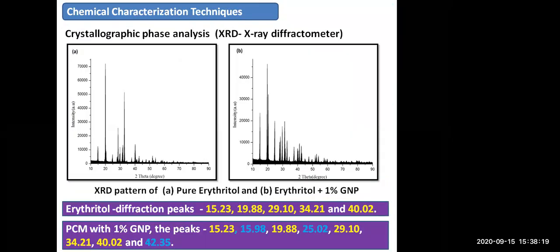The next one is the X-ray diffraction spectra for pure erythritol and erythritol with the 1% nanoparticle, shown in the figure. The crystal size was calculated to be 35 nanometer, and the lattice strain was 0.0062 for pure erythritol. It can be concluded that the addition of the graphene to erythritol has peak intensity approximately similar to the erythritol, and indicates the graphene produced no crystal changes in the erythritol.